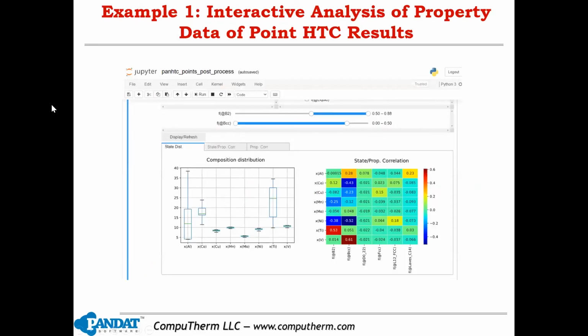And here is an example. Basically in this example, as a user, you can define, let's say, I want B2 phase to vary in the range from 50 to 88%. And the BCC phase to vary from 0 to 50%. And then when you vary this fraction, you can see from the left bottom figure how the composition of each element will change. So it basically tells you when your composition varies in this composition range, you will attain this kind of phase fraction. And the right bottom figure also tells you how each element will affect the fraction of each phase. Basically, a positive number means the element will promote the formation of this phase. And a negative number, of course, means it's not good for this phase formation, all right?